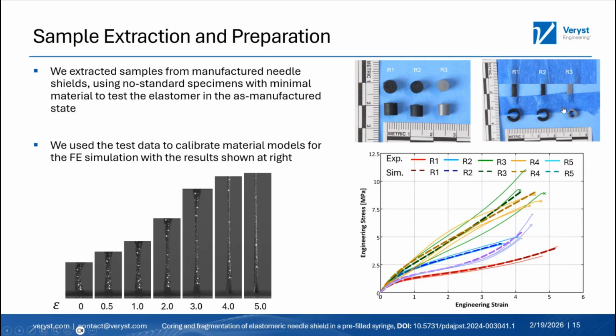There are 5 different color lines. It's a little bit messy there, but you can see the 5 different color lines for the tests that we ran on those 5 different materials. The solid lines are our experimental data, and the dashed lines are material model predictions. So we took that data and selected a material model to use in our simulation, calibrated to fit that experimental data, which you can see in the plot. These ones here match very well, and we're very happy with those matches.